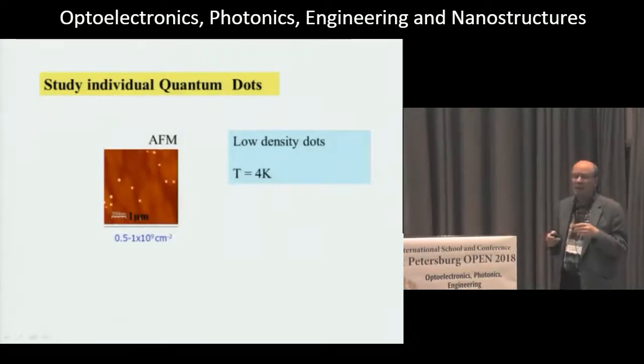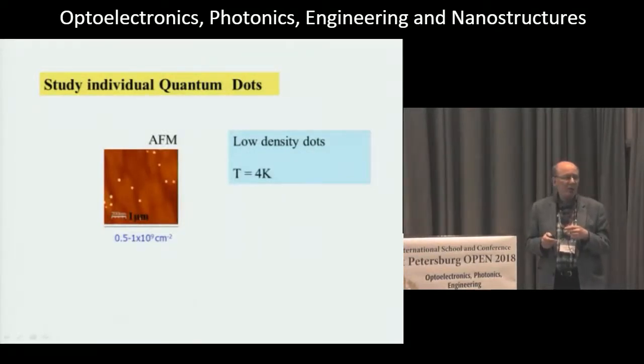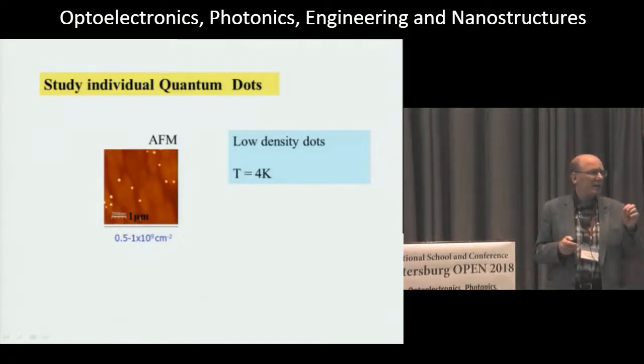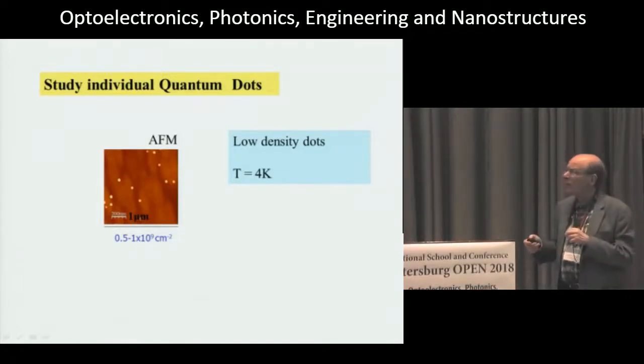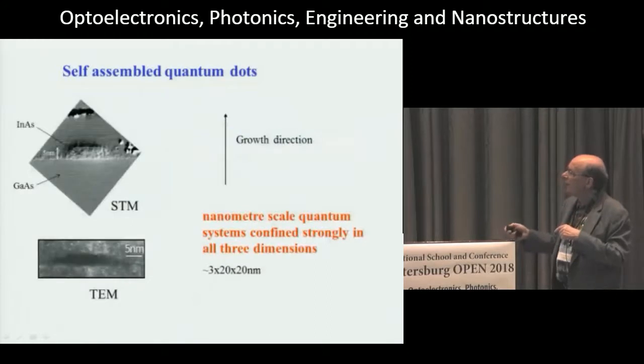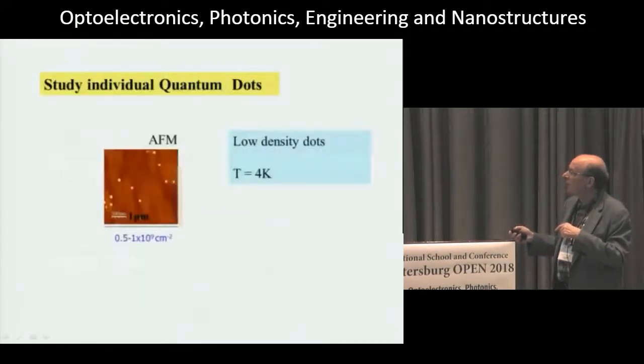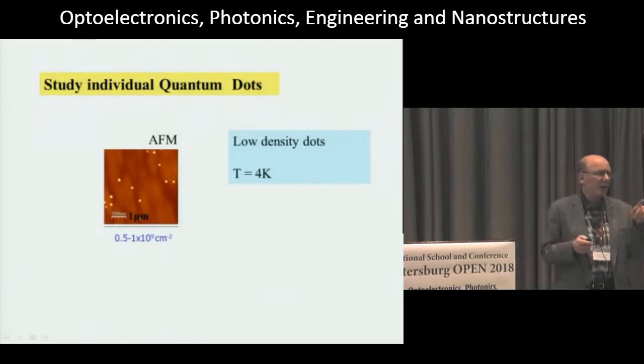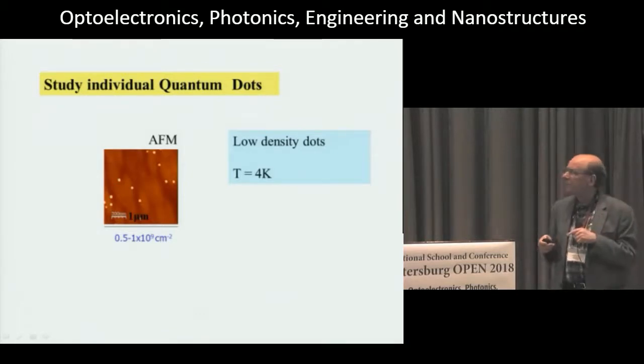So we're dealing here with individual quantum dots. So the growth, we need to access individual dots, and so the growth is controlled to give a relatively low density. So we're now looking down in the vertical direction now, and each white dot is a quantum dot. And we're going to be accessing what I'll explain in a moment are the favorable properties of individual quantum dots. And typically the density is up to about 10 per square micron.